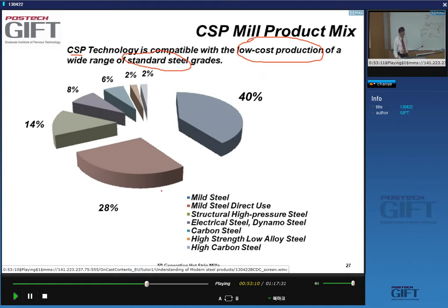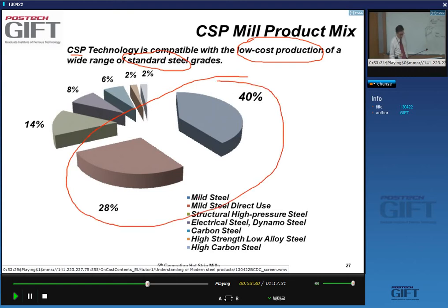And you can see here the typical product mix for a CSP-based producer. It's got all kinds of grades, but most of the production, as you can see here, 70% of it is just low carbon steels. So these are steels which we basically call commercial grades, yes, not demanding in terms of mechanical properties. So it's relatively easy to achieve the requirements in terms of composition, microstructure, and properties.